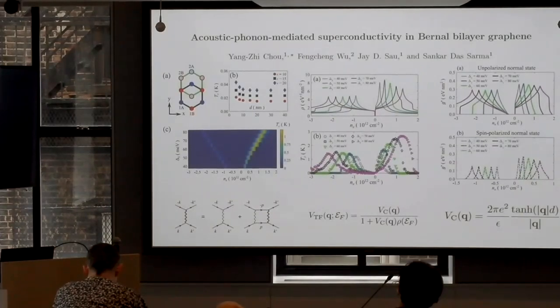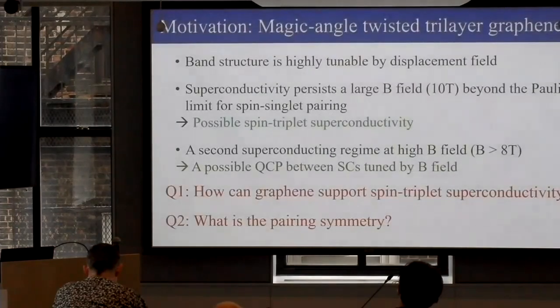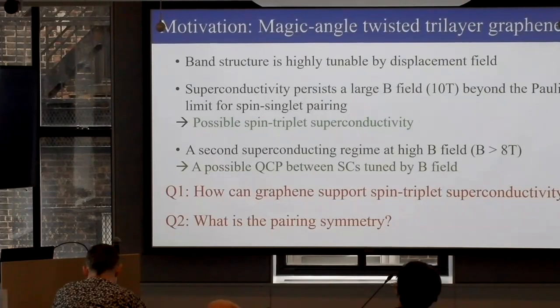So this is what the story is now. What's lambda here? Because v_F is not suppressed, there's no magic angle. So the lambda is the lambda for regular graphene here. But remember, the band structure, the Van Hove singularity, is what is giving the physics. So that's absolutely correct. If you take an electron gas model or Dirac gas model, you're not going to get any superconductivity here.